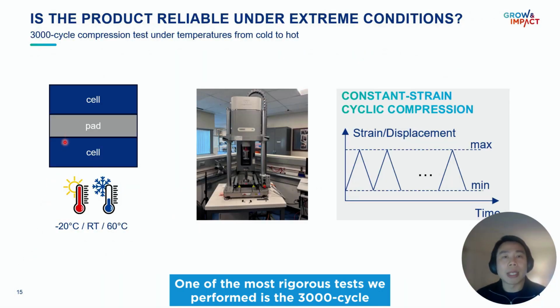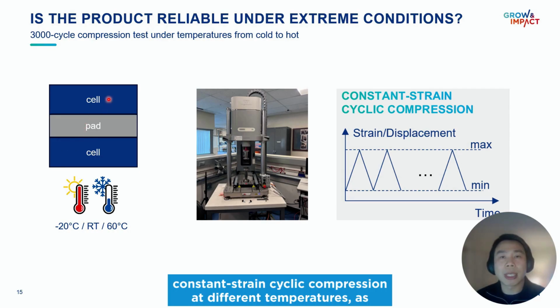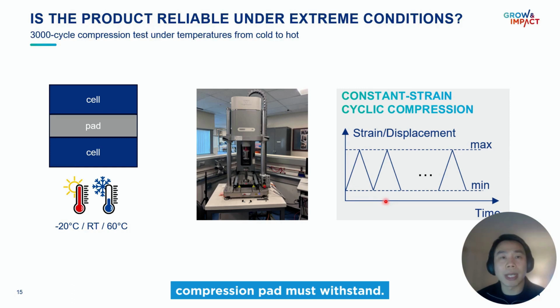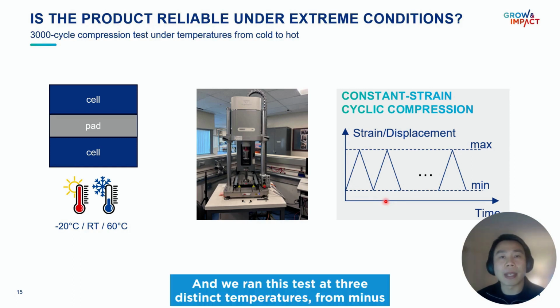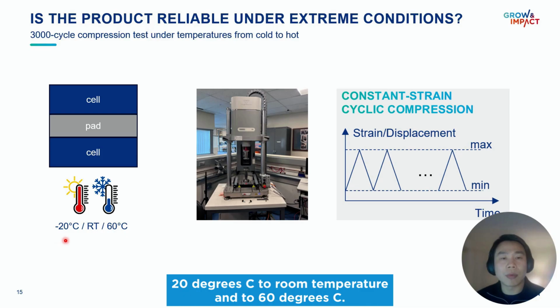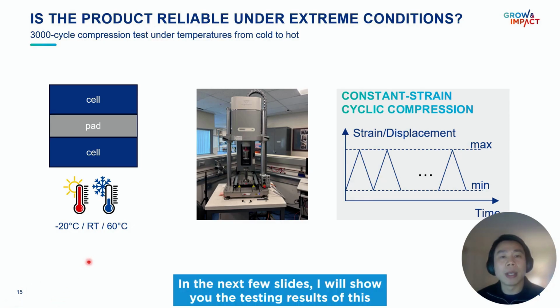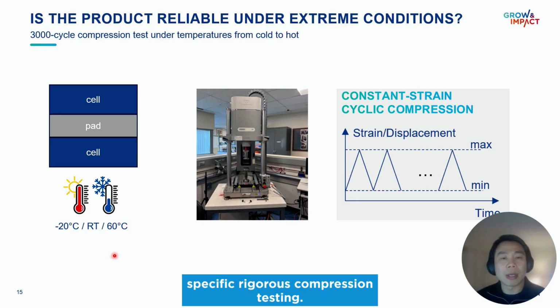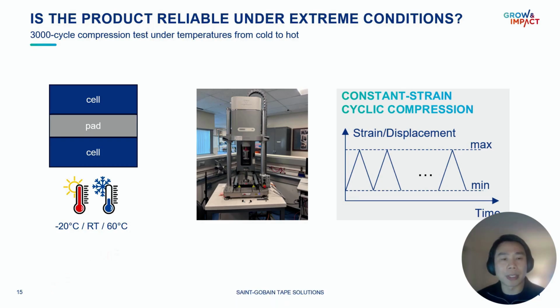One of the most rigorous tests we performed is the 3,000 cycle constant strain cyclic compression at different temperatures, as schematically shown here on this graph. This test simulates the years of cell breathing and swelling that a compression pad must withstand, and we ran this test at 3 distinct temperatures, from minus 20 degrees C to room temperature and to 60 degrees C. In the next few slides, I will show you the testing results of this specific rigorous compression testing.